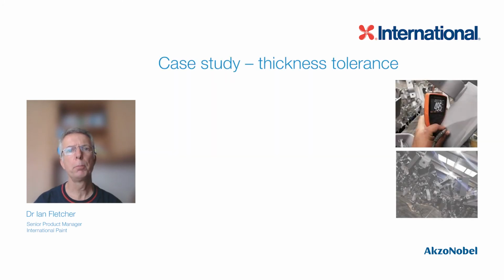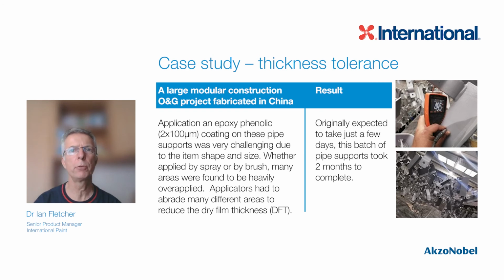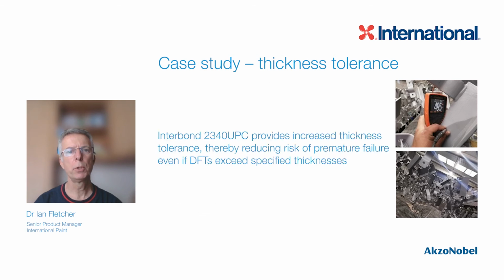The challenges of coating complicated process pipe shapes and sizes should not be underestimated. An epoxy phenolic specification of 2 times 100 microns was used to paint pipe supports for a large modular construction oil and gas project in China. Application by both spray and brush led to many areas being over-applied, and so the applicators had to abrade all of these areas to reduce the dry film thickness and bring them into the required specification tolerance. The coating job that was supposed to take just a few days ended up taking 2 months to complete. As Interbond 2340 UPC provides increased thickness tolerance, the risk of premature failure, even if DFTs exceed specified thicknesses, is greatly reduced.